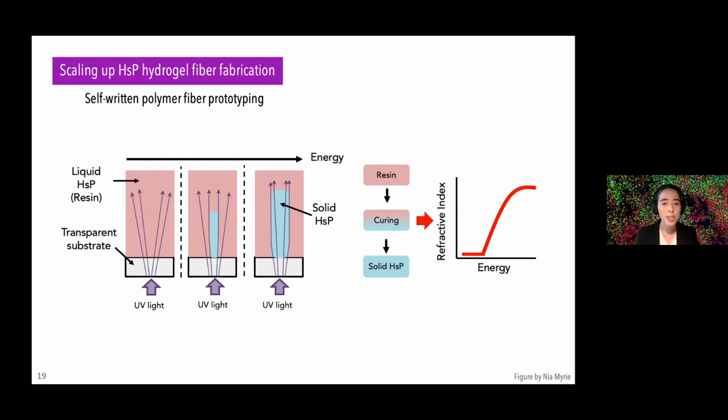This process continues and intensifies, forming these polymer fibers until reaching some saturation as the polymerization reaches completion. So various experimental parameters and material properties can be tuned to intensify this light focusing and extend the propagation of the fibers.